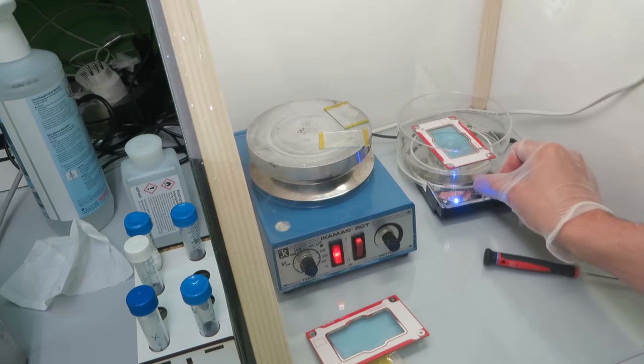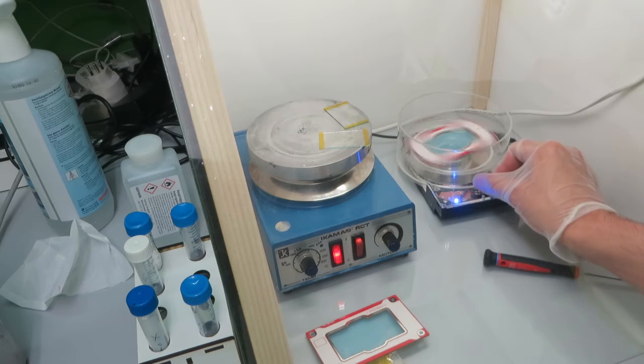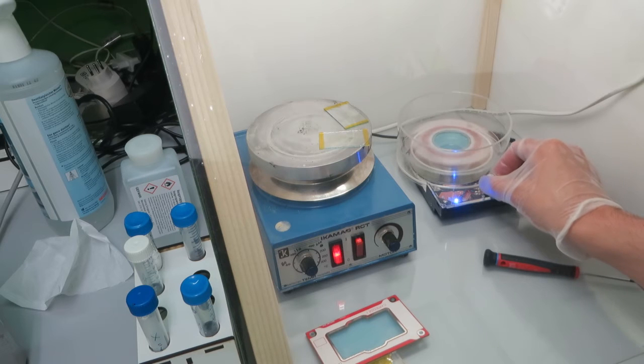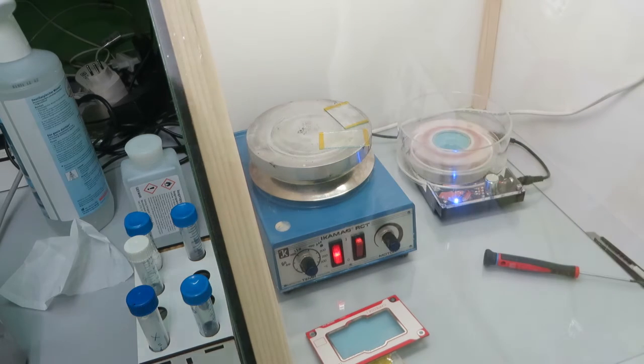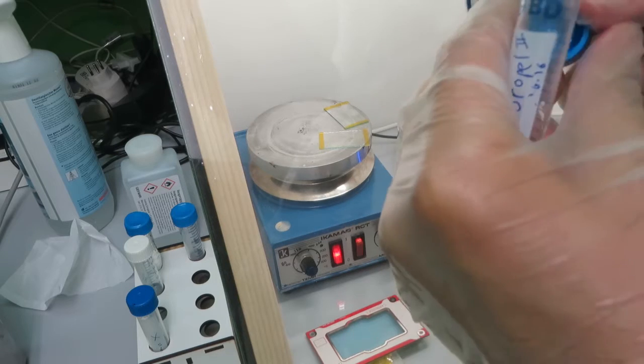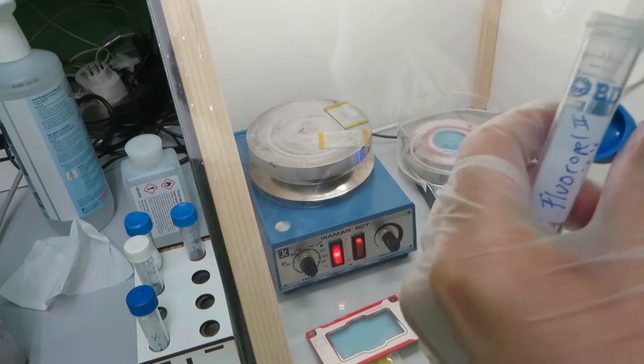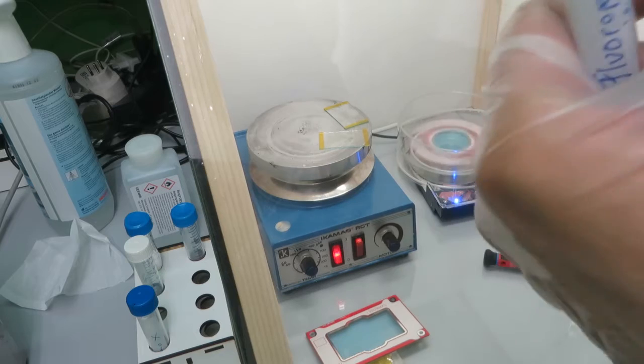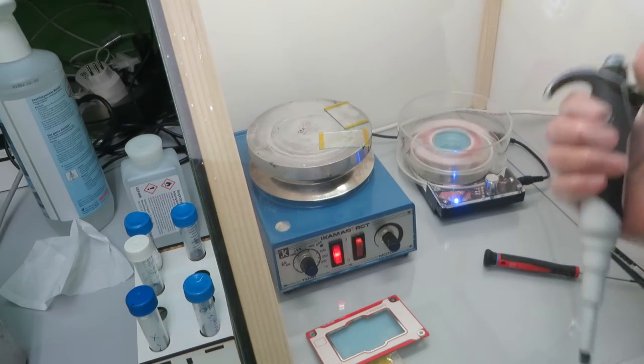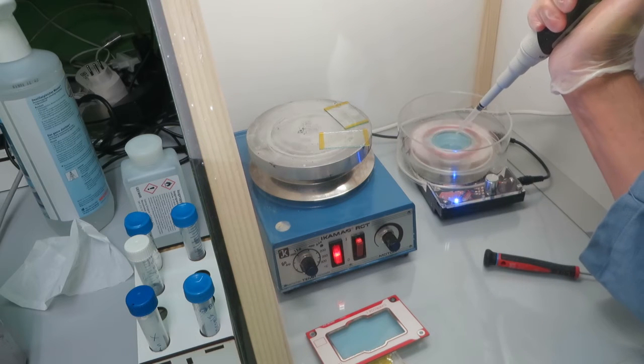Once the carrier is installed, I spin it up and then apply the liquid coating. The coating I use is Fluoropel from Cytonix. It's a fluoropolymer solution and I use about 150 to 200 microliters and I spin it on the rotating carrier or on the rotating foil.